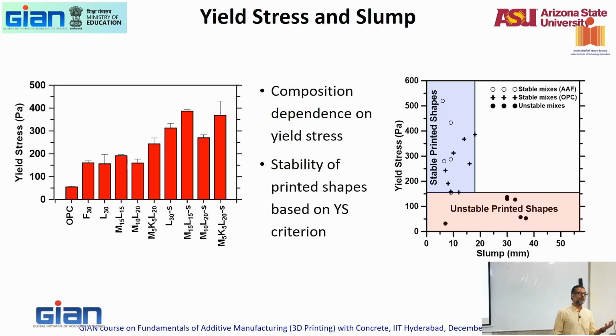Why? Not just particle size effect, but also the effect of clay, which has the ability to hold on to the water and not allow water to the rest of the mix so that it'll become much stiffer. So with metakaolin, that's what you see. With all these mixes, it is simply the effect of the more number of particles, more number of particle contacts, more energy required to break the flocs, more stress required to break the flocs. Correct? That's what you're seeing.